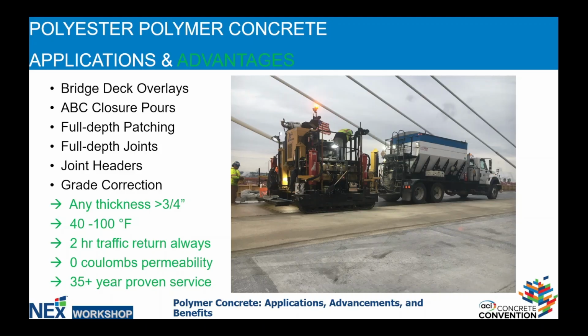A recent job I was on, an overlay was about 1.5 inches thick for over 500 linear feet of bridge deck overlay. That was a recent job I was on in North Carolina. So the temperature ranges 40 to 100 degrees. On smaller patchwork, you can get a little bit colder. We can go a little bit warmer depending upon the need, as well as the ability of the installers to adjust the cure rates and make sure that this material is still workable during its installation process.